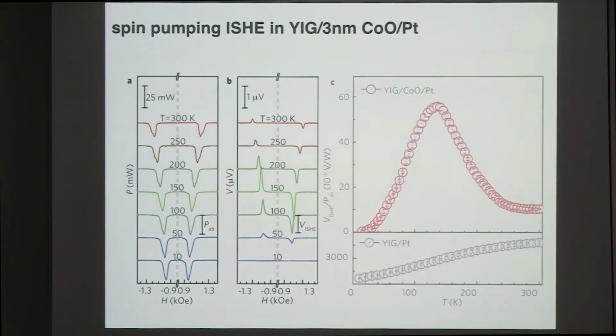So we just extract this peak position and plot it here. It looks like something like this, so obviously it's a peak, right? And we also double checked the structure without this CoO layer. It just monotonically goes down. Maybe there is some argument for why it goes down like this, but obviously there is no peak.